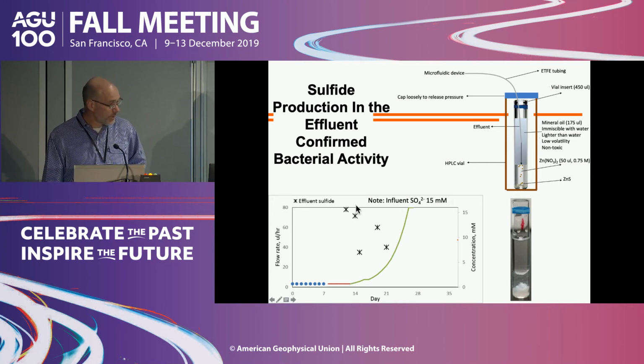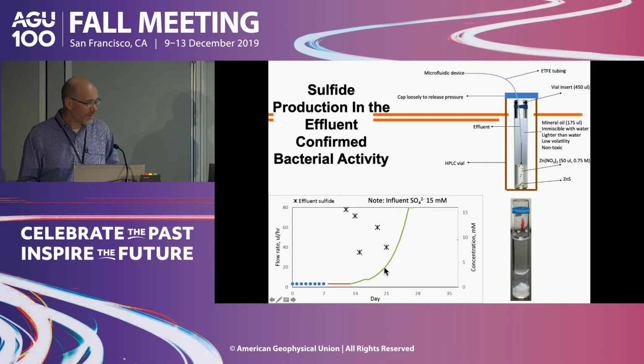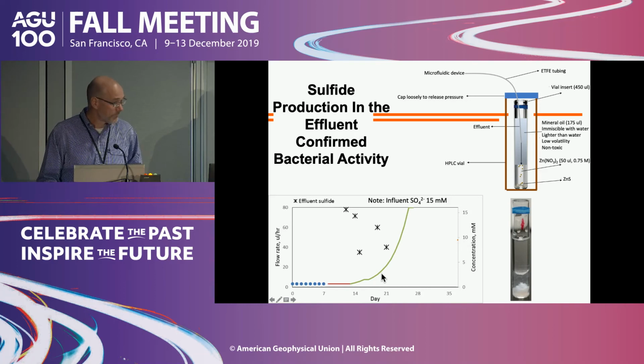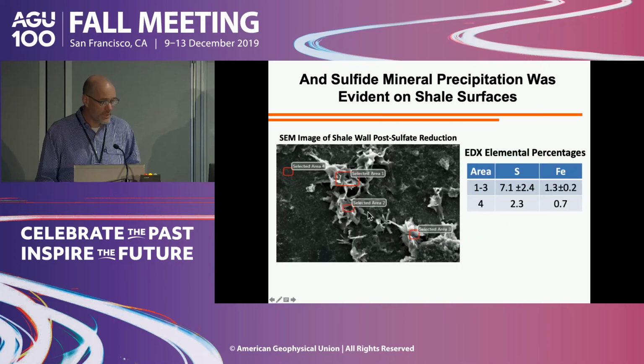What we found is that at the low flow rate, we had essentially all of the sulfate converting to sulfide. As the flow rate went up, we had some sulfate which appeared to be unreacted. I don't know how reliable these are, if our accuracy is within a factor of 2 or 1. The volumes are so small that this could just be fluctuation in the data. So I can only say that we have reaction occurring, but I can't say with confidence how much. We also saw these sulfate minerals, as you would expect, basically iron sulfides precipitating on these shale walls.